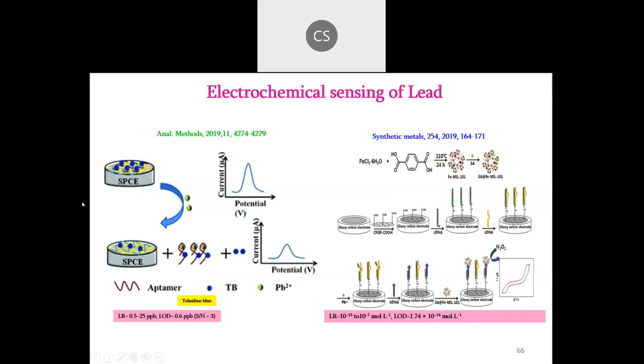This is one example based on nanoparticle-based sensing of the lead ion using an aptamer. You can see this is a screen printed electrode loaded with this nanoparticle. So in the absence and the presence of this lead ion, you can see how this current value drastically varies. Based on this current and this particular potential, this developed sensor can reach 0.6 parts per billion level of lead in this particular system. In a similar way, another method reported using an iron based nanomaterial can also be utilized for sensing with very low detection limits.